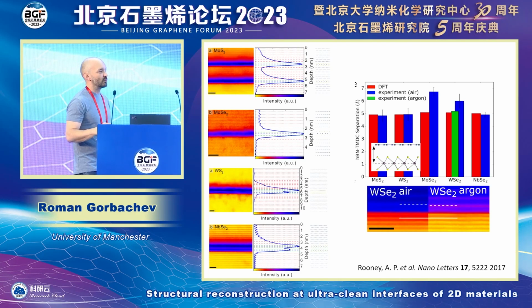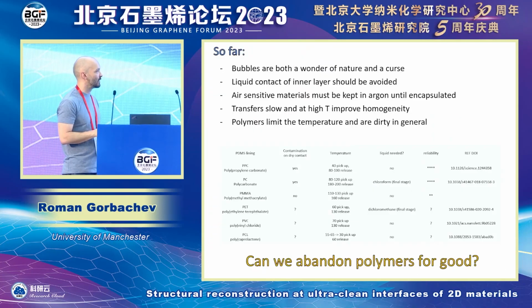So the glovebox really moved the field for another 5 years, and then we reached this point where we now have a lot of other materials like magnetic materials, trihalides, which are too sensitive even for a glovebox. So we basically reached another big problem where we really, really need to go to ultra-high vacuum. And so here's a short summary with all these polymers that you can use and you can distribute to your students if they're learning to do this technique. But yes, so in short, we need argon if we are working with very sensitive materials. We are transferring as slowly and at as high a temperature as possible to remove the contamination.